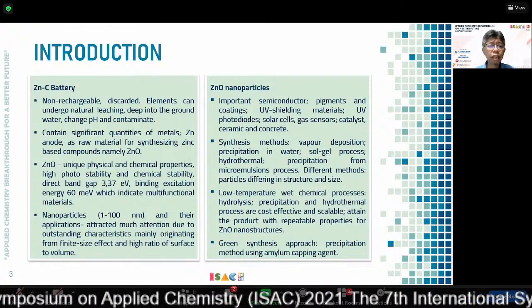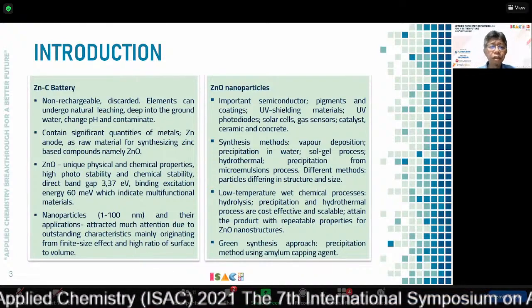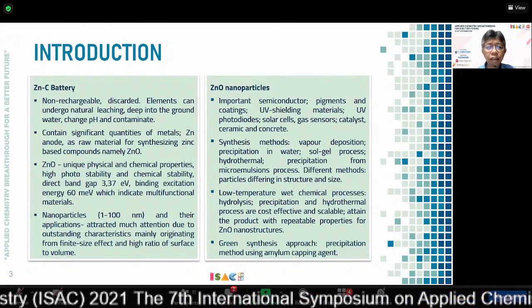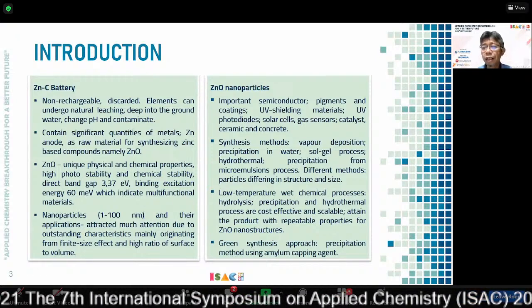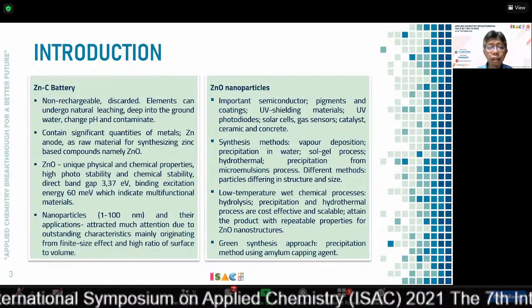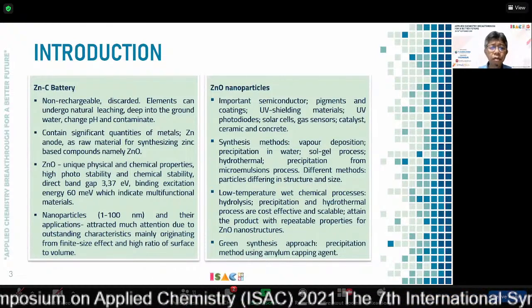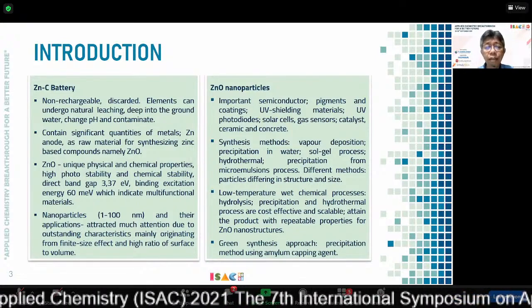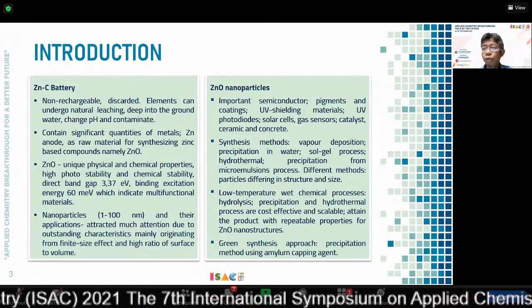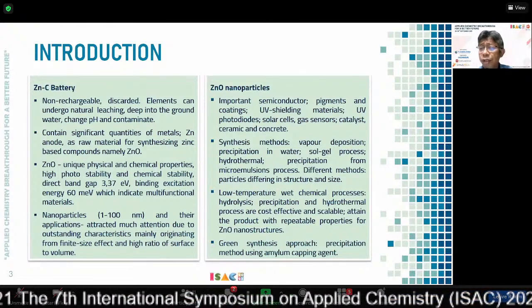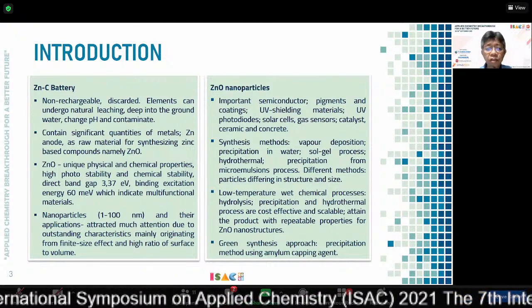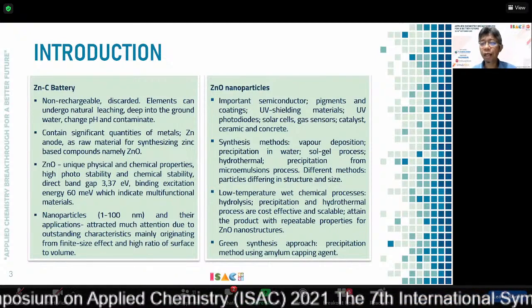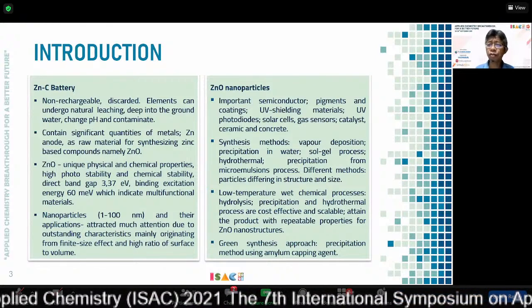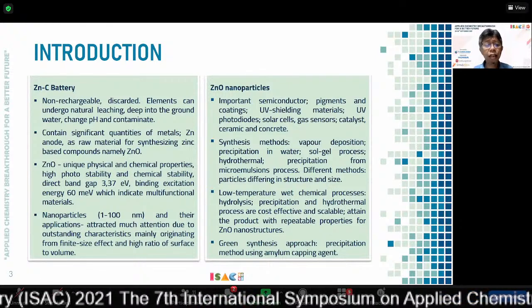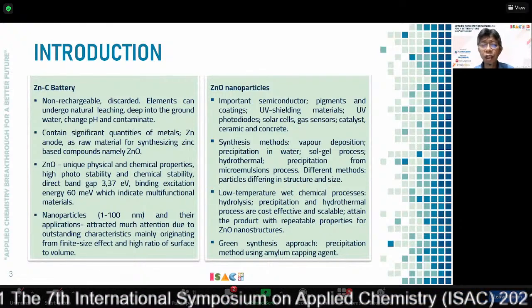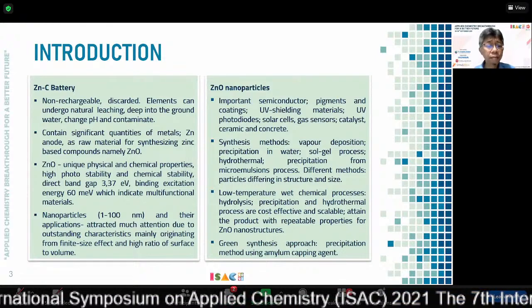On the other hand, if we look at the inside of the spent batteries, it contains significant quantities of metal, such as zinc, that can be a potential raw material for synthesizing zinc-based compounds like zinc oxide. As we know, zinc oxide has unique physical and chemical properties. It has high photostability, high chemical stability. It has a direct band gap of about 3.37 electron volts, and it also has a binding excitation energy of about 60 millielectron volts, which is even larger than other structures.